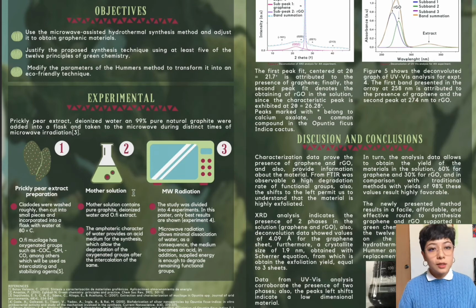Second, the mother solution. Mother solution contains pure graphite, deionized water, and Opuntia ficus indica extract. The polar character of water provides an acid medium for the synthesis, which allows the degradation of the oxygenated groups after the intercalation of the same. Third, microwave irradiation. The study was divided into 4 experiments. In this poster, only the first results are shown because of time.